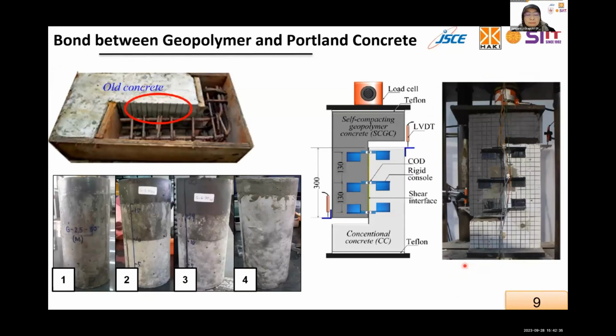This one. And it has a very great bonding system to calcium-based material. So for example, if we have an old concrete, and then after that we attach the geopolymer concrete, it will have a very good bond. And it is also very interesting to see that it can cover conventional concrete as a patching like here, and also like a cover. So it can act like a protector for repairing or jacketing for old concrete.